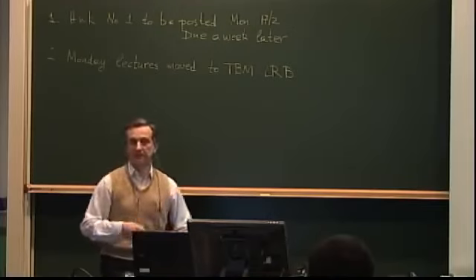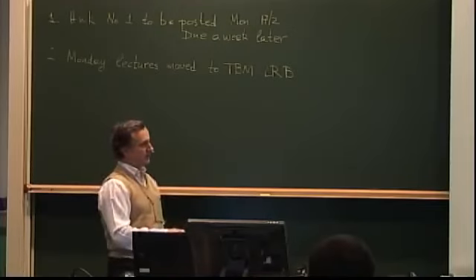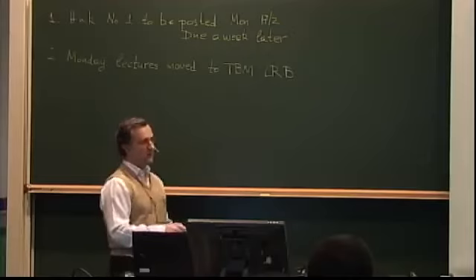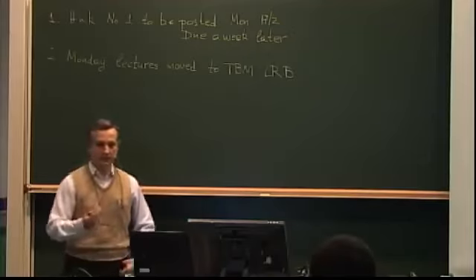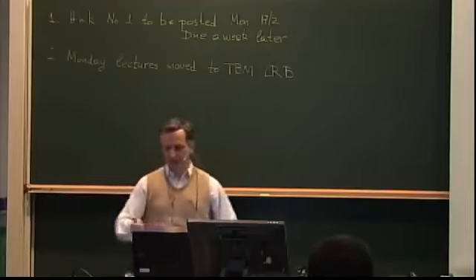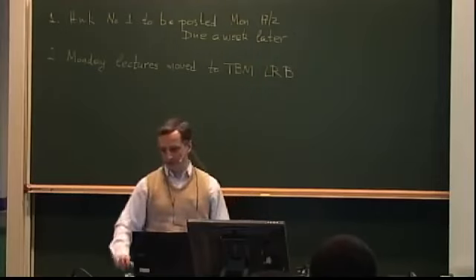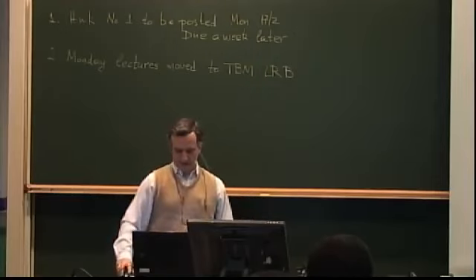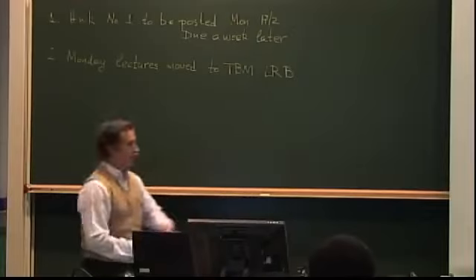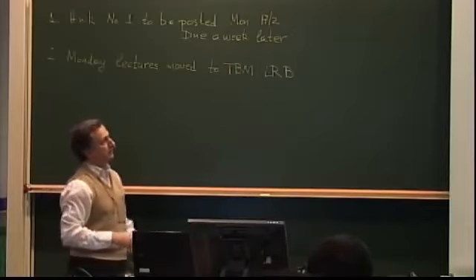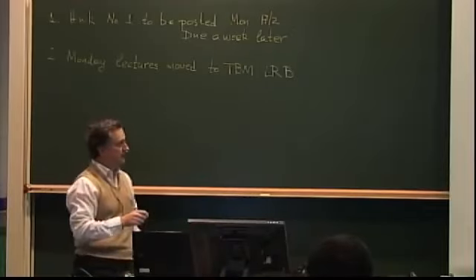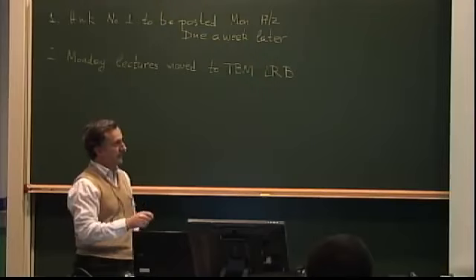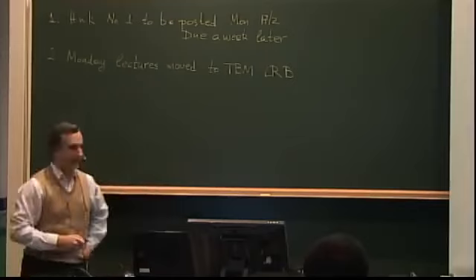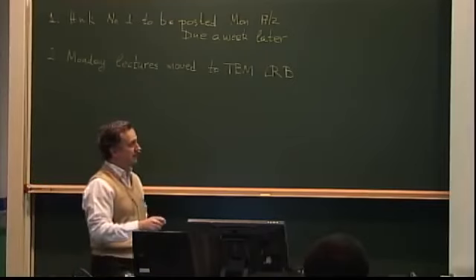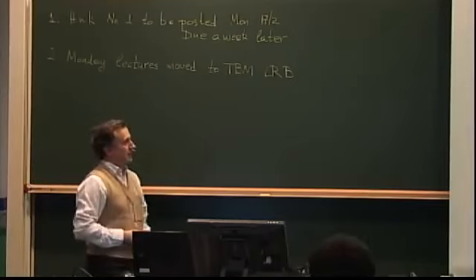Not for every laminate, but in general for laminates for which this term A16, or this integral here, is non-zero, that would be true. In metals, you cannot have that. You cannot have a uniaxial load and cause shear strain. So if I did it for the other two equations relating stresses and strains, I would get two more equations that in matrix form gives us the so-called membrane behavior, where the in-plane forces are related to the in-plane strains.